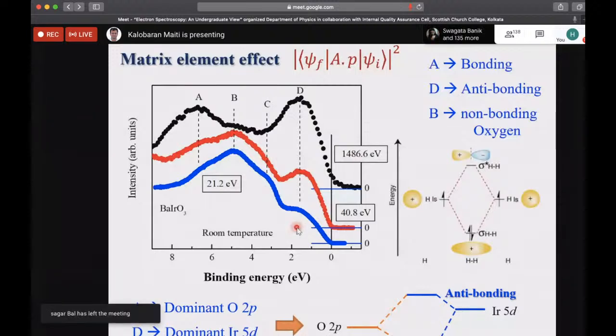Another conclusion that you can draw here is that since this one changes much more significantly in intensity at this energy compared to here, it means that this one has a much larger iridium 5d contribution compared to this. So from this spectrum, you can draw this kind of energy diagram where oxygen 2p and iridium 5d may not be at the same energy level. Because if they were at the same energy level, their change should be similar. But that's not happening. Since this one is changing much stronger, this one has more contribution from iridium. So oxygen 2p and iridium 5d must be like this, and this is the anti-bonding and this is the bonding. And in these states you can see there is no iridium D contribution, so it must be only oxygen which is not bonded. So these are called oxygen non-bonding states. So that way you can actually learn about the bonding, anti-bonding and non-bonding states in a material using photoemission.